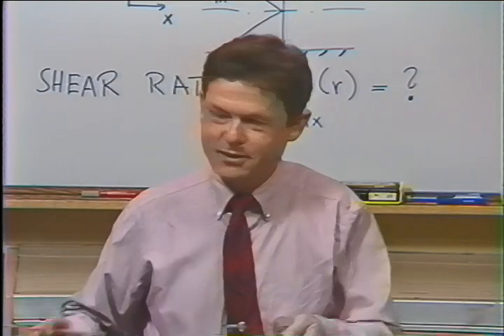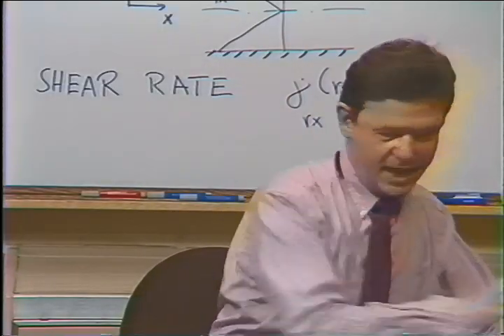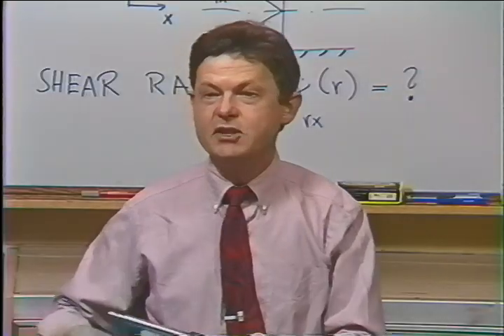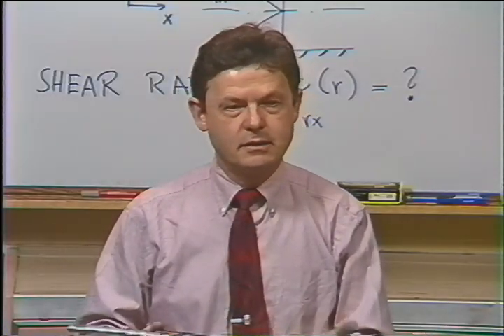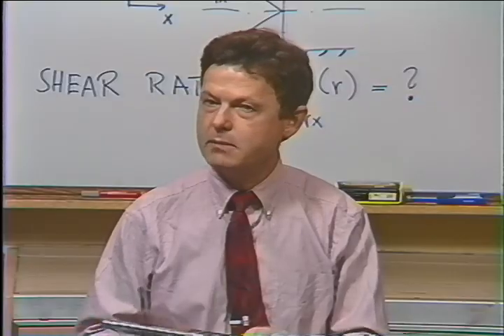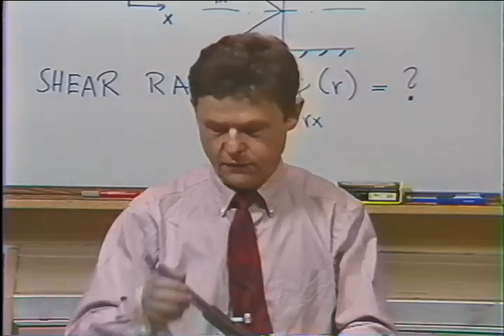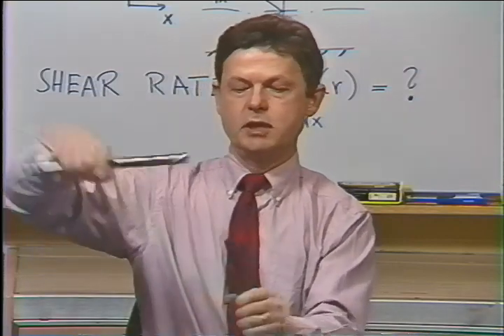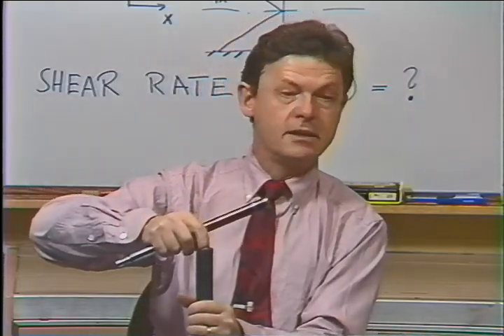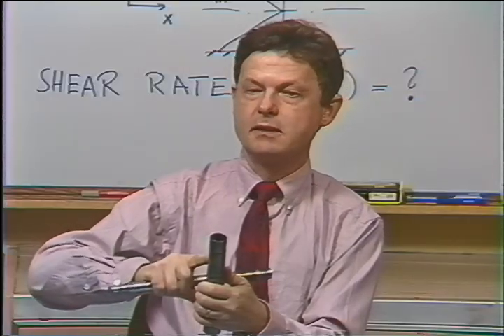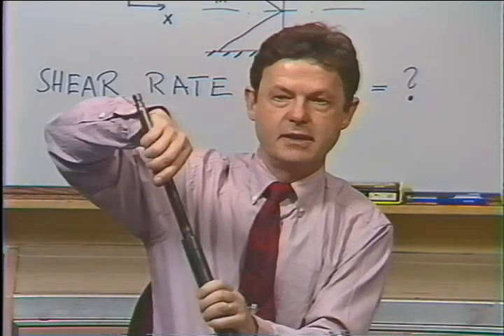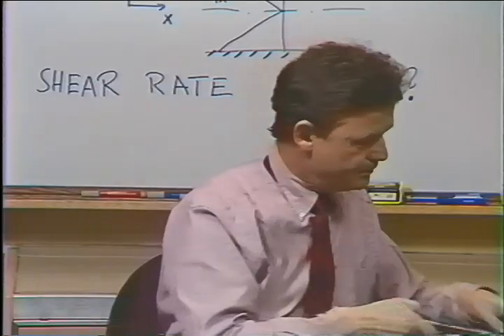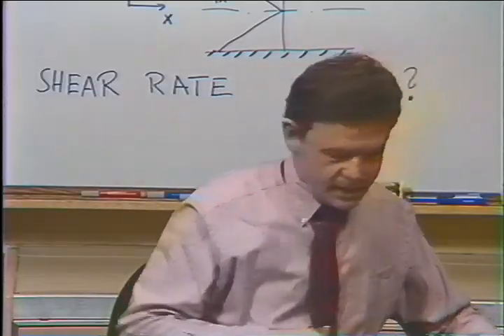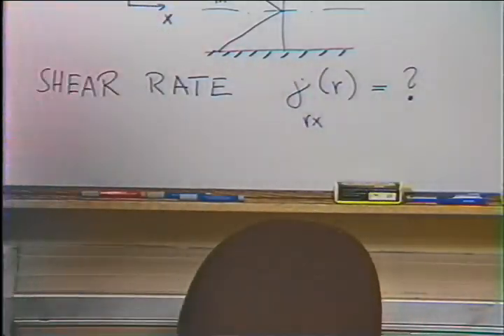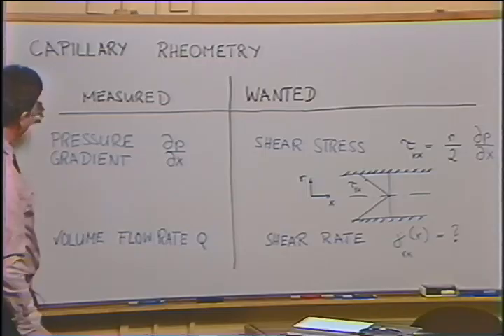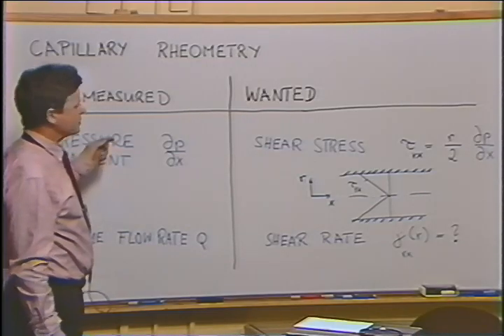So that's the hardware involved in capillary rheometry. Of course, there's a heating jacket put around, and the forces have to be accommodated with a large frame, but basically that's it. For filling the capillary rheometer, you would pull the plunger, put in maybe a plug of material, wait 5 or 10 minutes till the temperature is equilibrated, and then you start the extrusion experiment, and you go.